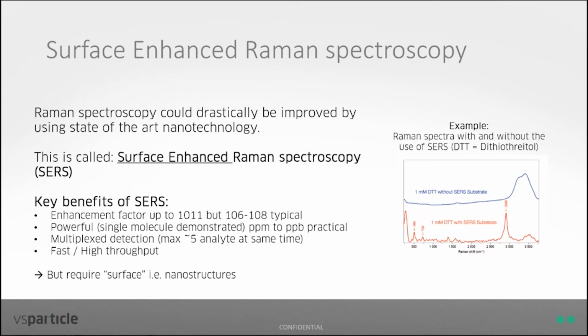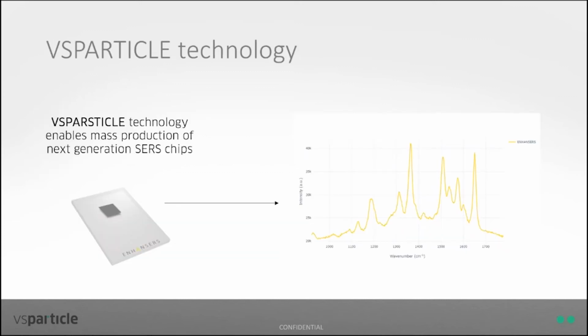But as mentioned, it requires this surface or this nanostructured layer, and that's also where VSPARTICLE comes into place. So with our unique patented technology, this Nanoaerosol processing technology, we are able to print uniquely structured nanomaterials directly on this glass substrate, which have been proven to give huge enhancement. So this SERS substrate is a product that VSPARTICLE has taken into production and brings to the market via our new brand, Enhansers. And on the right, you can see a nice graph where we have analyzed rhodamine 6G, and you see the nice enhancement peak coming off of the Raman spectroscopy.